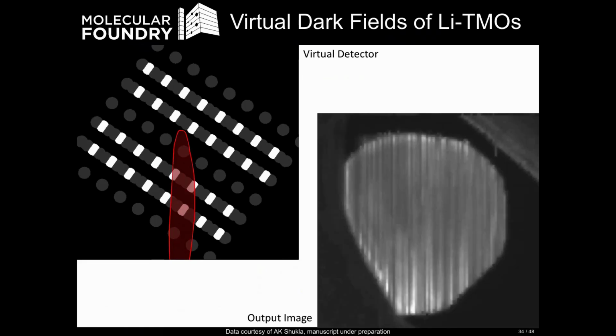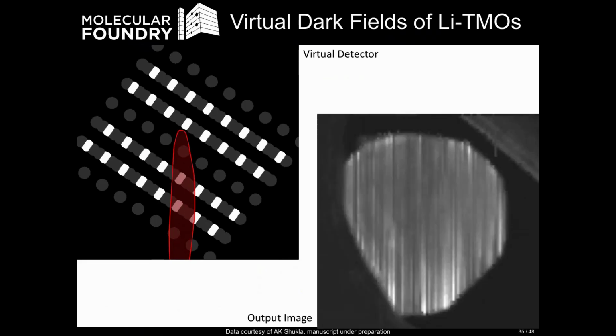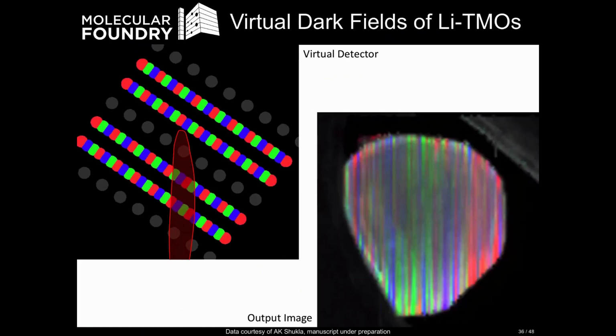And if I move to the next one, or the next one, I can pull out all three variants simultaneously here. And then finally, I can make a merged image in red, green, and blue that shows the density of these stacking defects and their overall size here. And again, this is just from a single 4D-STEM experiment collected over this entire particle.